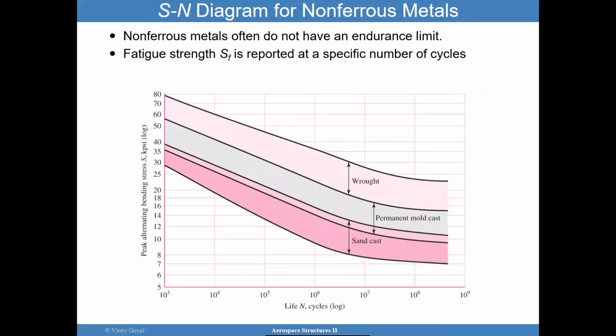The SN diagram for non-ferrous materials will typically look like this. For wrought, a little bit higher. Again, here you have the peak alternating bending stress, and here on the x-axis, I have the number of cycles to failure. The fatigue strength is typically reported as a specific number of cycles, and permanent mold cast will be lower, and sand cast even lower.